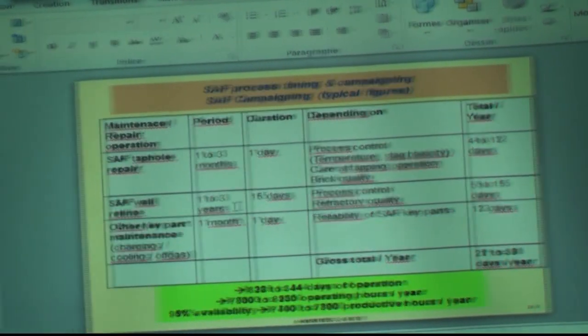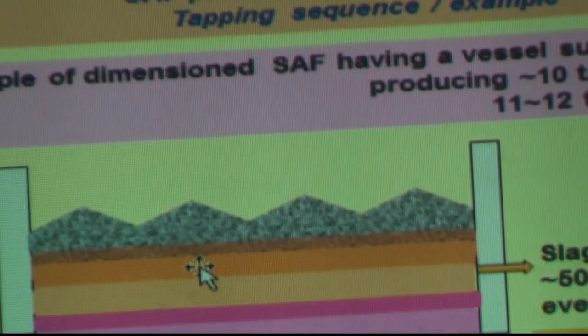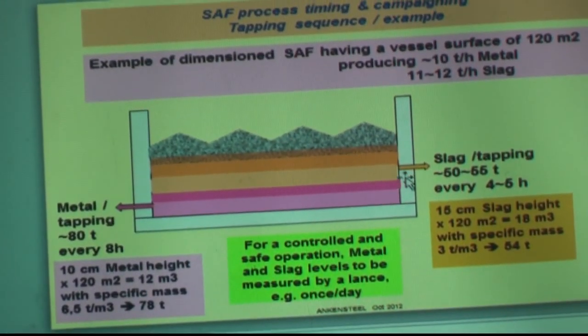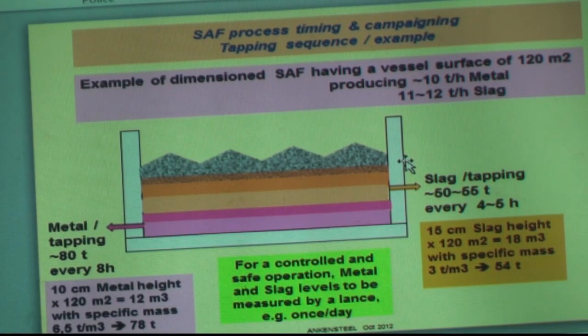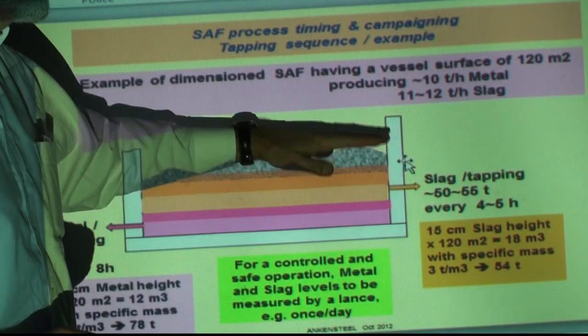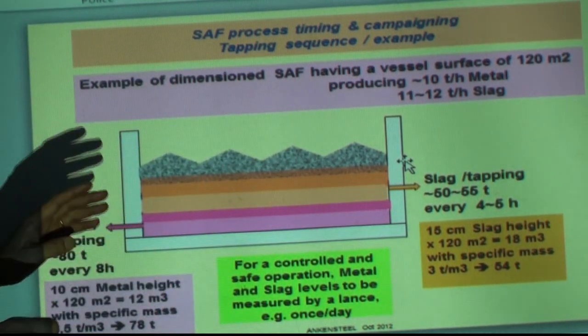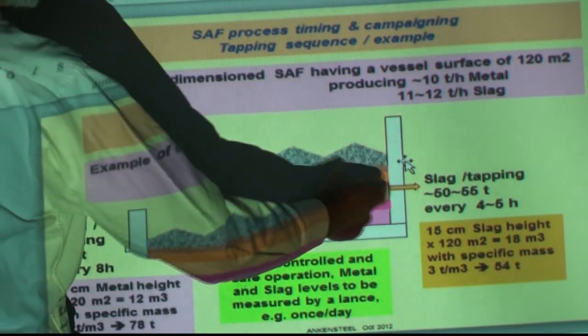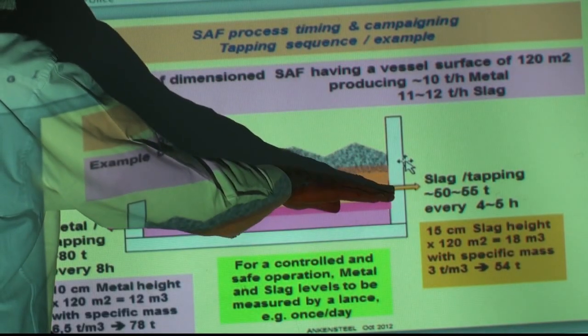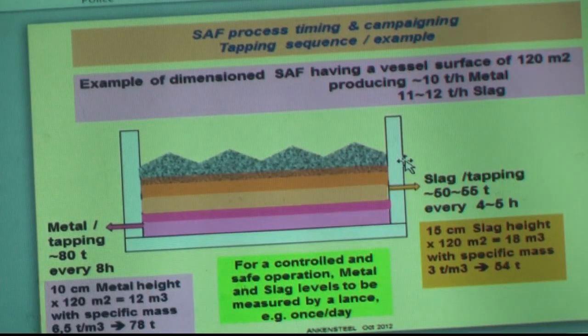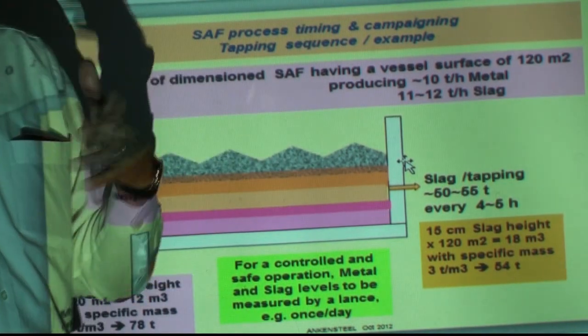SAF will last mostly 1 to 3 years. And during a tap hole repair, it's not exactly what I said, because during a tap hole repair, they stop charging, and after you let the slag descend, it mostly is a slag tap hole repair. So you don't charge, you let the slag descend until here, then you tap the metal, so the slag will be even lower than the tap hole slag. Then you can do some repair. The remaining slag will be, let's say, frozen, and you can change a few bricks here.